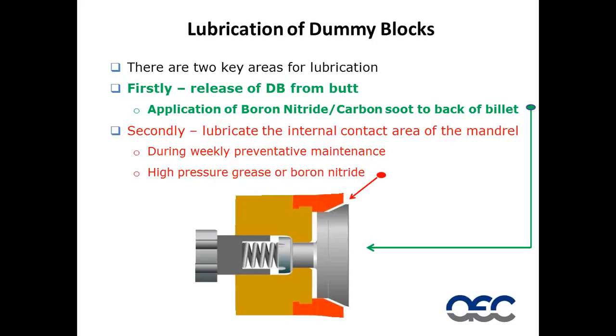We also recommend at least one time per week taking the dummy block off the press, cleaning it thoroughly, and either putting high pressure grease or boron nitride powder or liquid on the pressure area between the angle on the mandrel and the angle on the ring or flange of the dummy block.